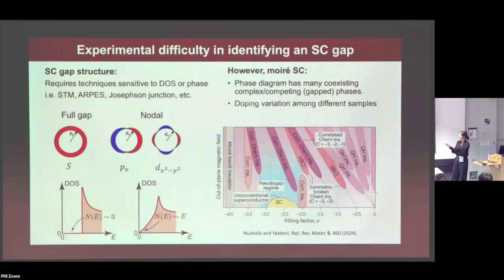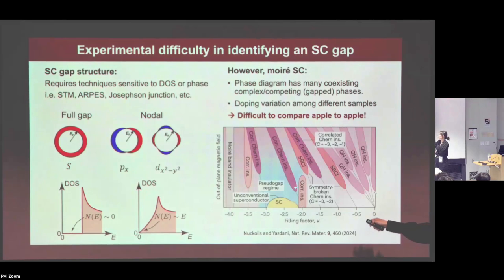And on top of that, it doesn't help that each device might have a little bit of doping variation because of the unfortunate twist angle disorder, or just the details of the device, you end up with different twist angles in general. So it's kind of hard to compare among different sets of experiments, or even similar sets of experiments but done on different devices. It's hard to have an apple-to-apple comparison. For example, the fact that there must be superconductivity next to the correlated insulator is kind of universal in all the devices, but the exact extent of the superconducting dome, how much it overlaps with the correlated insulator, up until where in doping is the superconducting gap, up until where in temperature is the pseudo gap, all these details are quite varying in different devices and different setups.